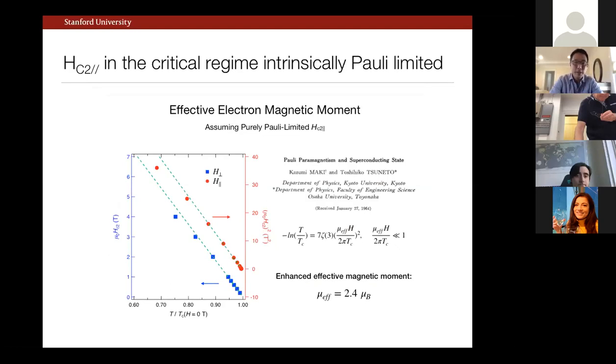So given that it doesn't seem to matter what the thickness of the actual sample is, and yet we see this nice square root dependence, an alternative explanation is that this is intrinsically Pauli-limited in the in-plane direction. These are actually old ideas. Namely, I'm now plotting this critical regime for the in-plane upper critical field scaled as HC2 squared here. And in this case, rather than being geometrically confined, you're intrinsically limited by the Zeeman scale. The interesting consequence is that the scale of this HC2 variation, this would also give you a square root of T, can give you a measure of the effective magnetic moment associated with the normal state electrons. So it's this competition between pairing versus Zeeman scale here. And we get an enhancement here, actually. This is the number we get from this T-squared fit. Okay, I'll come back to this in a moment.